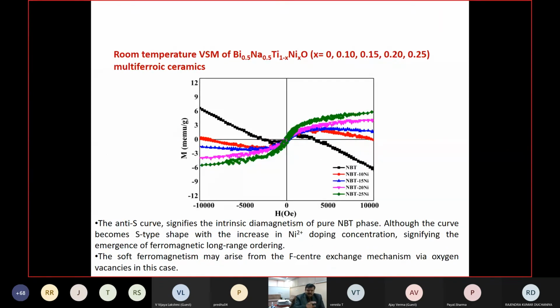And then he took the magnetization of the composite. Now I am talking about the composite. Composite means the combination of sodium bismuth titanate and nickel ferrite. And what he observed for pure sodium bismuth titanate, the magnetic behavior is nearly diamagnetic, but with increase in the nickel doping, the magnetic features come into the picture. And for 25%, it is showing not a very good ferromagnetic loop, but not a very bad ferromagnetic loop. So it is showing the weak ferromagnetic behavior of the composites of sodium bismuth titanate and nickel ferrite.